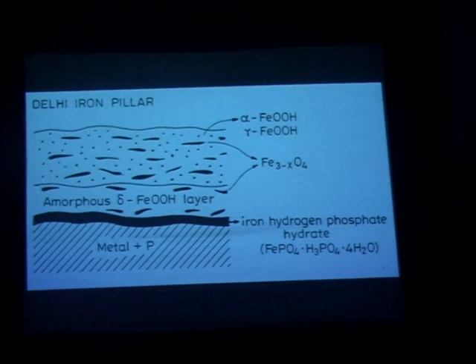In the case of Delhi iron pillar, we believe it is because of the phosphorus in the iron, and due to wetting and drying and wetting and drying, you form a phosphate layer, and once a phosphate layer forms, corrosion will practically come to a stop. Therefore, the reason for the corrosion resistance of the iron pillar is due to the formation of a protective passive film which resists against corrosion.